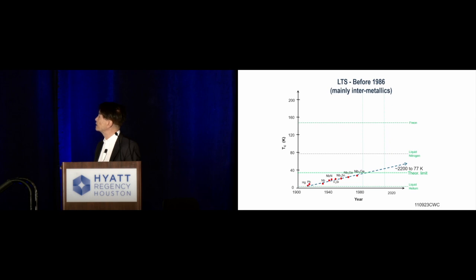For example, before 1986, if you plot TC as a function of time, it goes up like this. At that time, the highest TC was 23.2 degrees, in niobium-3 germanium. By extrapolation, to get up to 77 degrees, the liquid nitrogen temperature, you would not get it until 2200, and even with the very impressive improvement in medicine, it's difficult, at least for me, to live that long. At that time, experimentally the TC record was 23.2, and the theory predicted TC cannot go above 30 degrees Kelvin. During that period, there was a confidence crisis for most, but a few, and we were one of the groups, did not believe that.